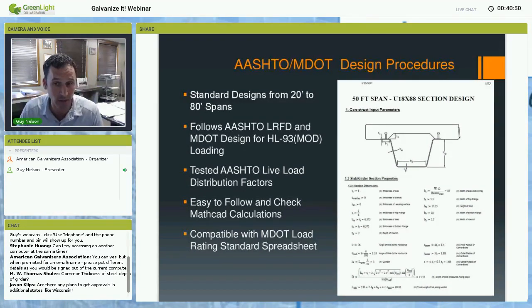Our thickness of the steel, we keep everything to 3/8 of an inch. Again, that goes back to the fact that strength is not a design constraint. The constraint is typically the live load deflection. So 3/8 is the minimum thickness typically used for flange elements, and we keep the whole tub girder at 3/8 of an inch thick. And again, depth of the tub girder we keep to span length over 25.